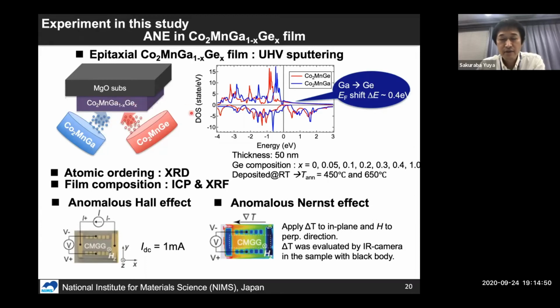And in our study, in order to change the degree of atomic ordering, we prepared two series of thin films. One was annealed at 450 degrees C, a relatively low temperature. The other was annealed at 650 degrees C to obtain higher atomic ordering. And we measured the anomalous Nernst effect by flowing the heat current in the in-plane direction in this film, and we measured the temperature gradient by using an infrared camera.